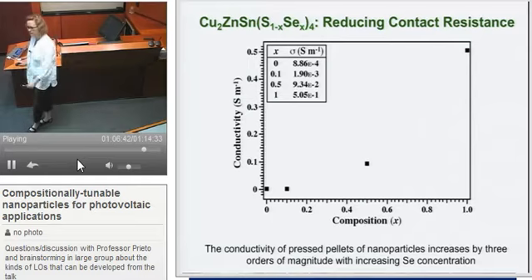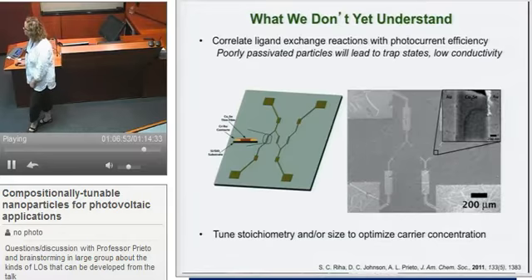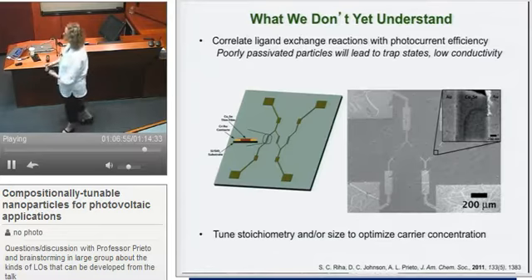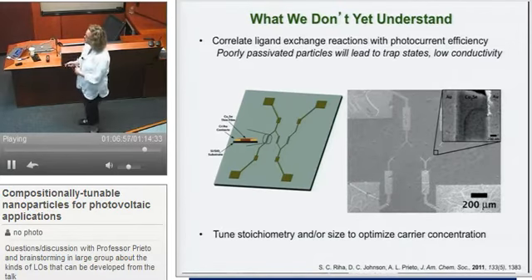In the paper you'll notice we listed, I think, 3 hypotheses for what the selenium is doing, and we were trying to be systematic about eliminating the ones that we could. We are doing a lot of work now on thin films of these nanoparticles using electron beam lithography to pattern electrodes. So this is a cartoon of what these patterns look like. If you zoom in, there are 2 gold electrodes, and we deposit nanoparticles on the surface.